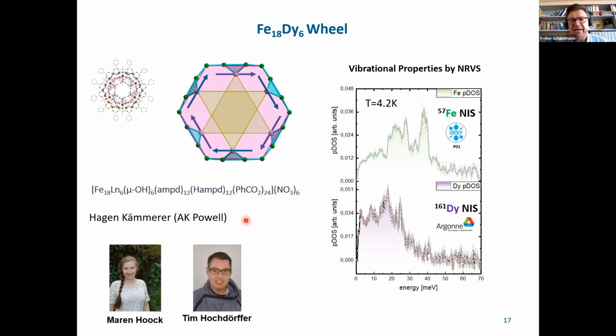And we wondered not only about the hyperfine interactions, but also about the phonons. And here you see a measurement done really at 4.2K on the dysprosiums at APS. And beforehand, we could measure iron 57 nuclear inelastic scattering, NRVS, on the iron systems. And we are at DESY, and we are right now in the process of evaluation of the data, with the calculations that are going on.